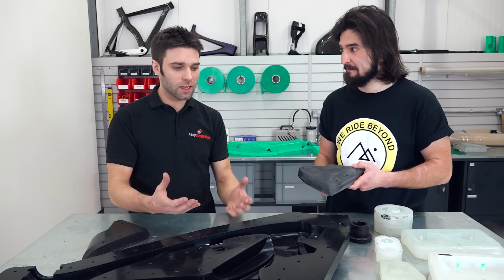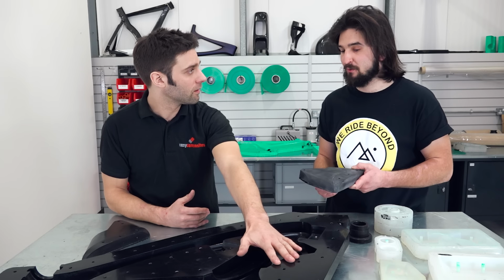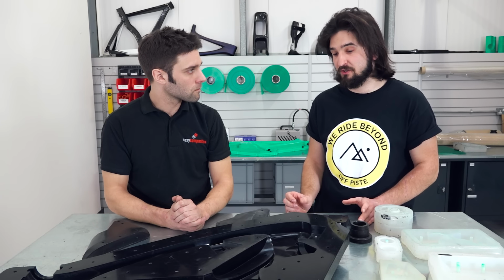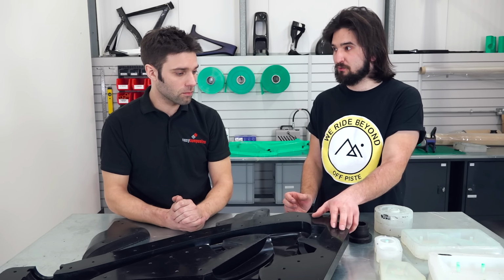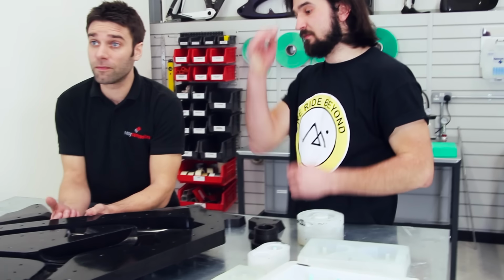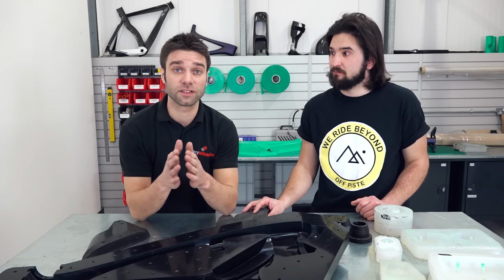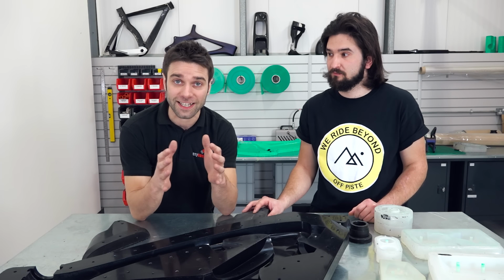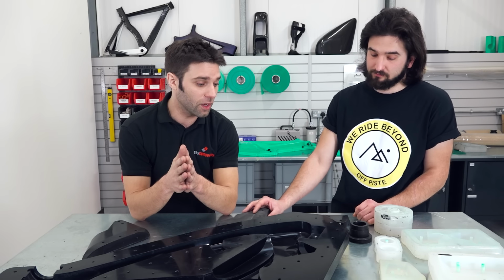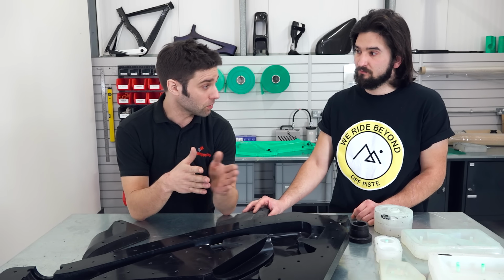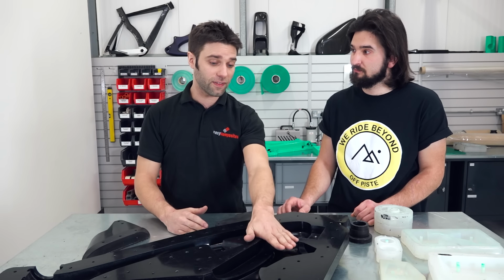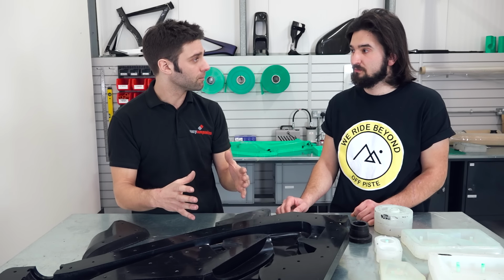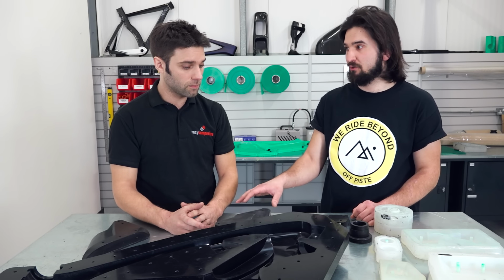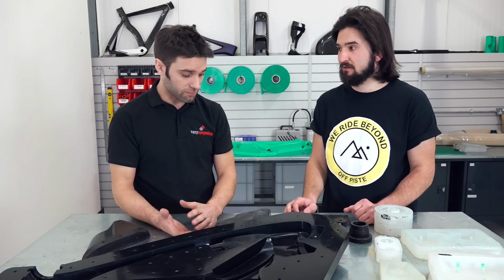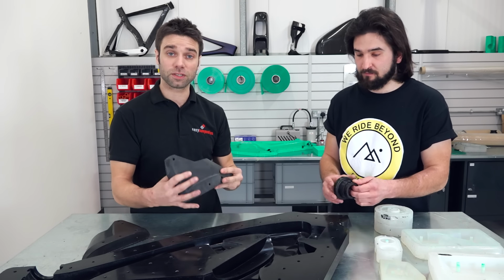Forgive me for asking, but why not just machine an epoxy insert? Well, as we mentioned earlier, epoxy expands under temperature, and we need something with a similar expansion rate to the tool. These tools are carbon fibre, and carbon fibre is well known for having a very low CTE, coefficient of thermal expansion, the amount it changes in size with heat. And epoxy model board, although it's quite stable, with a large insert like that it might cause problems through its expansion. So it's better to take it out of the equation. Right, okay. So these are graphite filled, high temperature epoxy inserts then.